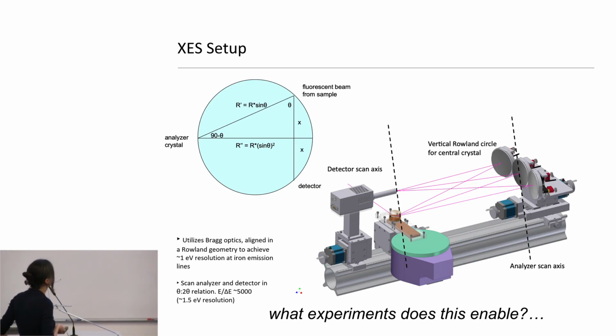Okay, but let's just look at the setup in a little bit more detail. I've kind of drawn this out so you can just see a different perspective on it, and so you can see the geometry. Because when we align these spectrometers at a beamline, we're actually sort of thinking of a sphere of intersecting what we call Rowland circles. And so we basically have fluorescence from our sample, and then we have our analyzer crystal. And that analyzer crystal is bent to have a radius of curvature that defines basically the circle that I'm working on. And then geometrically on that circle, I need to also place my detector.